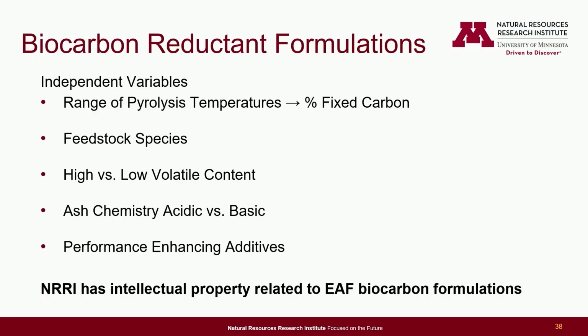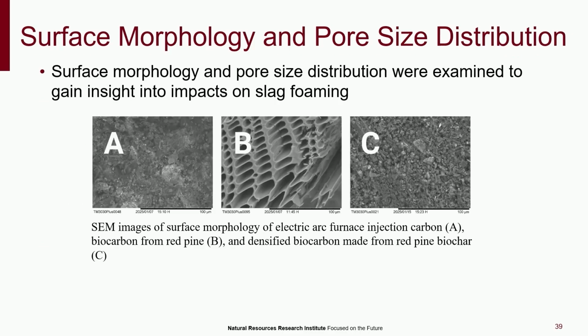So moving into results, we played around with a range of pyrolysis temperatures, which then would give you a range of fixed carbon percentages. We played around with feedstock species, high and low volatile content, our ash chemistry being acidic and basic, and then we also added performance enhancing additives. NRRI has intellectual property related to EAF biocarbon formulations. We also have a team that does a lot of biochar characterization. I'm going to highlight our surface morphology and pore size work, but if you're interested in any of that, come check us out. We got a lot more than what I'm talking about today.